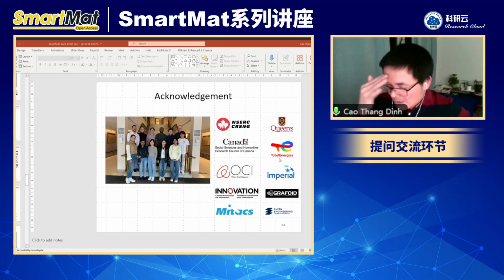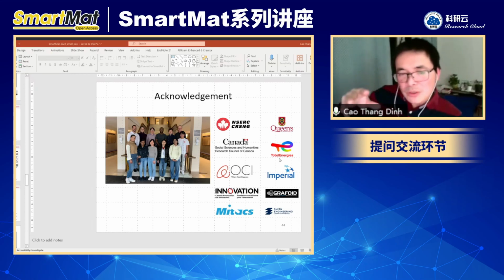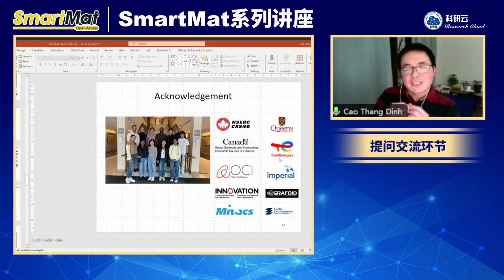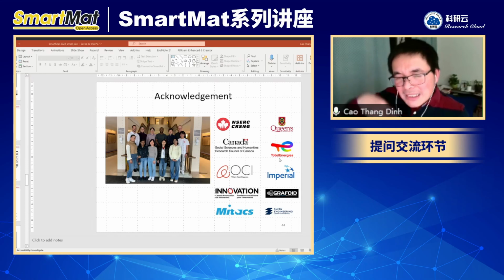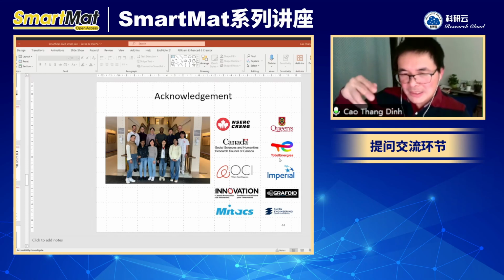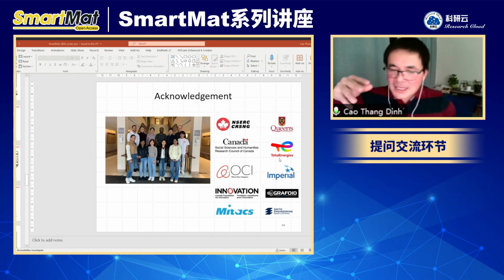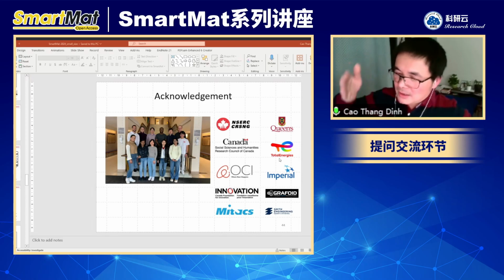But now it is a little bit complicated, because when you do the CO2 conversion, you have the copper surface exposed to the alkali condition. Maybe you have hydroxide on the surface, right? Often in that condition, the copper tends to oxidize directly from copper metal to copper 2+ ion. So in order to slowly oxidize to make the oxide phase like Cu2O, for example, you may need something on the surface which is more stable. Or you can control the local environment on the surface so that when you oxidize, it prefers Cu+.